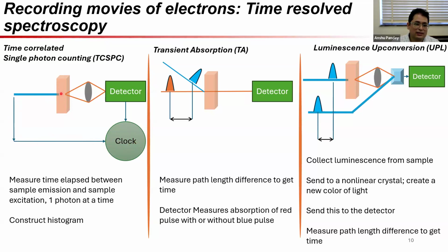Meanwhile, a laser pulse has reached the sample, the sample has absorbed it, and eventually, whenever the sample decides, it releases a few photons, one of which is directed to this detector. As soon as this detector receives that photon, it sends a second pulse to this clock, which is a stop pulse. So this allows us to measure when the laser actually fired and when we actually received a photon from the sample. We repeat this process thousands or millions of times, depending on what we are doing, and we construct a histogram. What this tells us is the lifetime with which the sample is emitting. So this essentially gives us some sort of kinetic trace of what is happening to the dynamics of the sample.